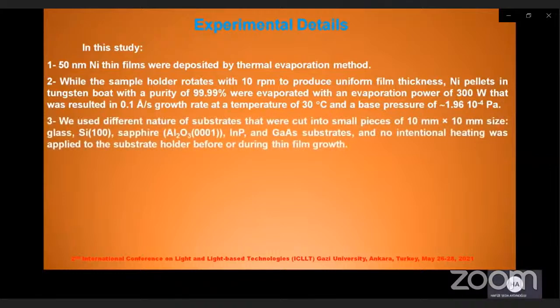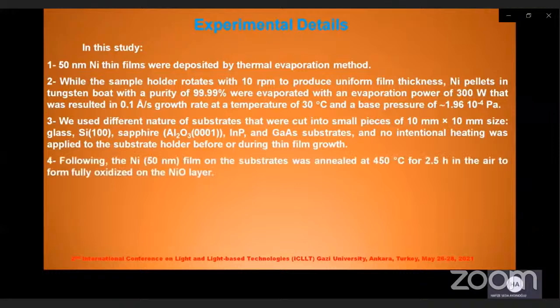We used different substrates that were cut into small pieces of 10 mm times 10 mm size: glass, silicon, sapphire, indium phosphide, and gallium arsenide substrates, and no intentional heating was applied to the substrate holder before or during thin film growth. Following the 50 nanometer nickel film on the substrate, samples were annealed at 450 degrees centigrade for 2.5 hours in air to form nickel oxide layer.